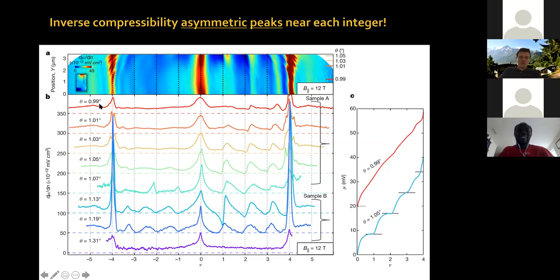But now you take traces at slightly larger angles, 1.01 degrees, 1.03, 1.05. By the time you get to 1.05, 1.07, actually already at 1.03, you see that a lot is happening, and in particular, a lot is happening for the electron filling factors. If you get to 1.13 degrees or so, as you can see in this blue trace, lots of features are happening for both electron and hole filling factors.